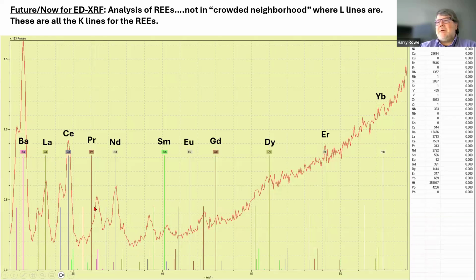As we can see, lanthanum, cerium, praseodymium is hiding underneath here, but you can deconvolve it with some software all the way up to terbium. Can't get lutetium. But with this technique of a larger XRF, much more powerful, over 100 kilovolts, we can do this. And my hope is that we see this get a lot more use in geological studies, especially for provenance.